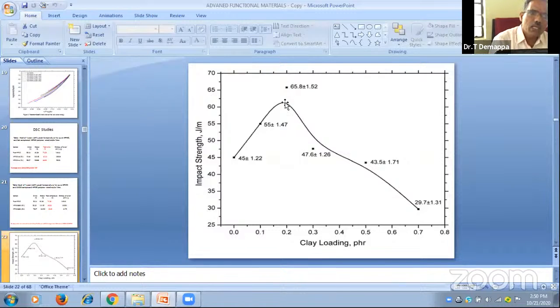The maximum mechanical, that is impact strength, is found at 0.2 phr because of the improved interfacial bond strength, interfacial adhesion between the clay and the epoxy. Afterwards, there is agglomeration. There is no proper wettability between clay and epoxy resin, so agglomeration takes place. Big zones are formed, and it is not sufficiently wettable, so improper curing takes place. Hence, the mechanical property decreases.